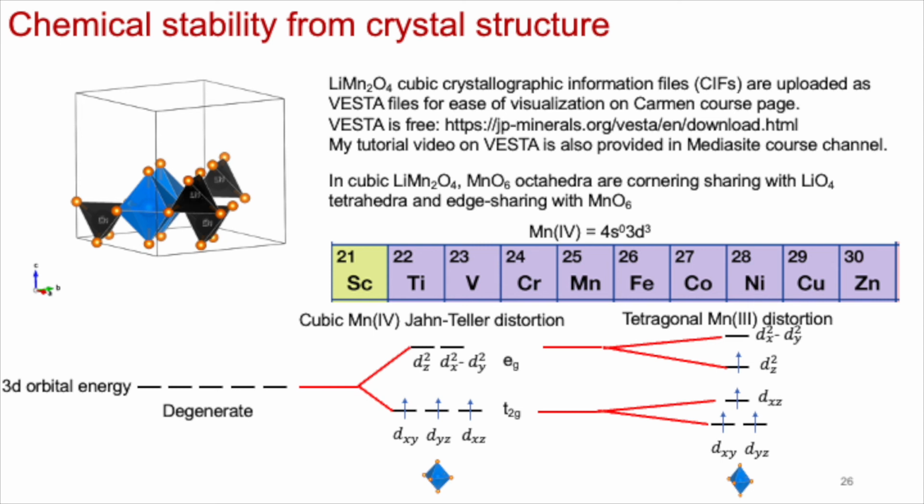Well, this configuration has 1 extra electron, and the configuration is going to be tetragonal now. It's no longer just in this octahedral environment. So in fact, the orbitals will split again. The EG will split again, and T2G would split again in this particular tetragonal symmetry. And there are 4 electrons, so you fill it up: 1, 2, 3, 4.